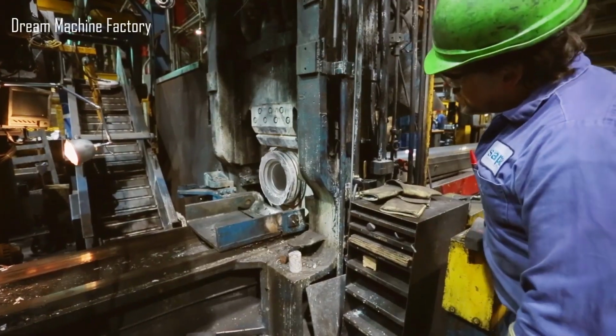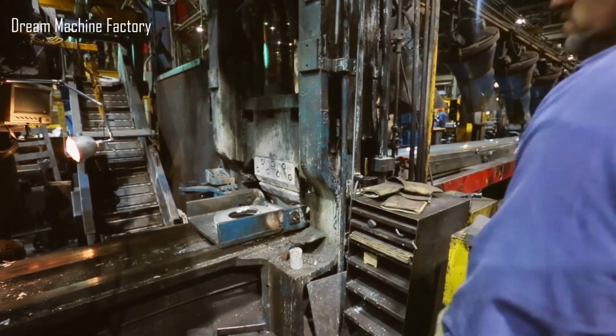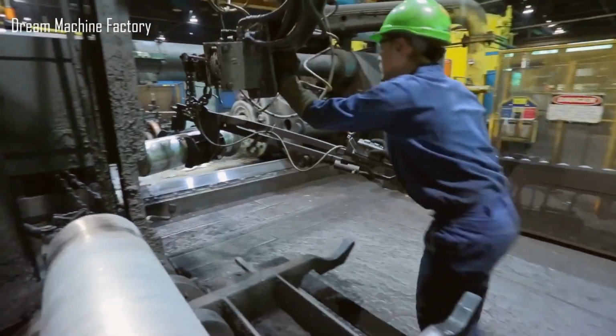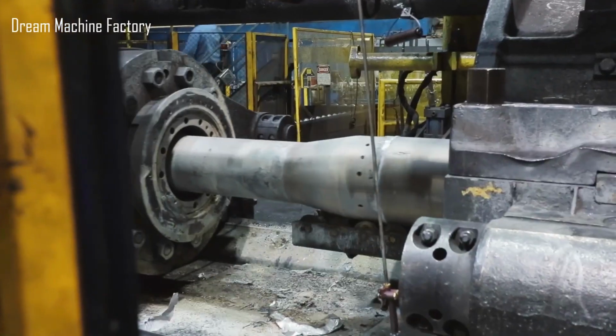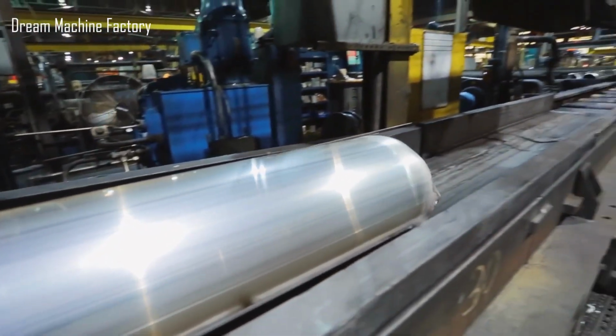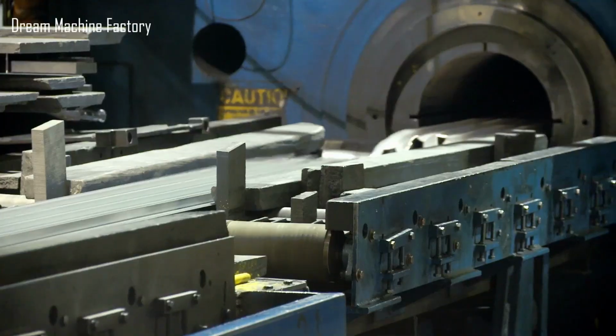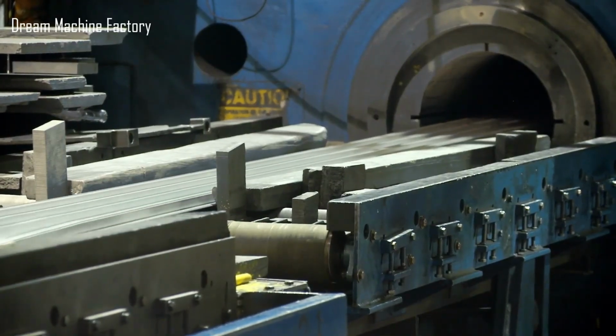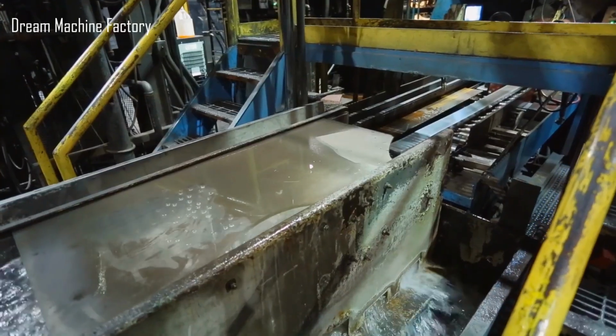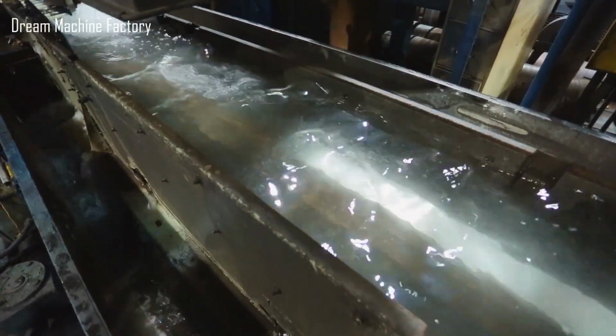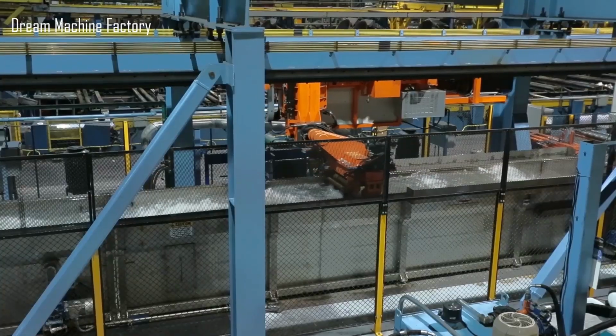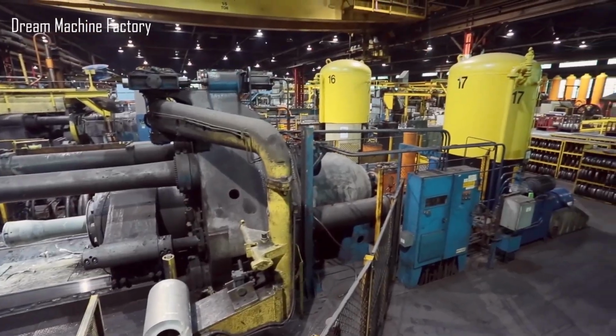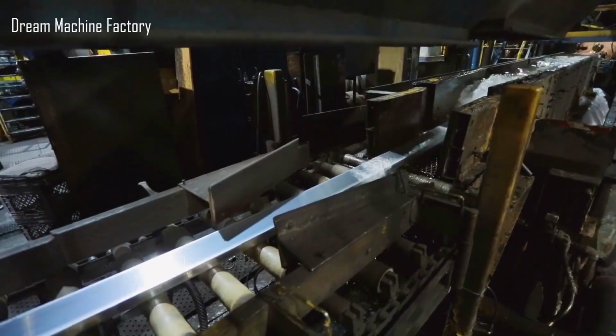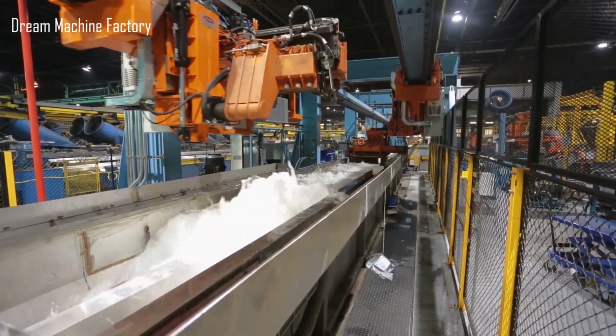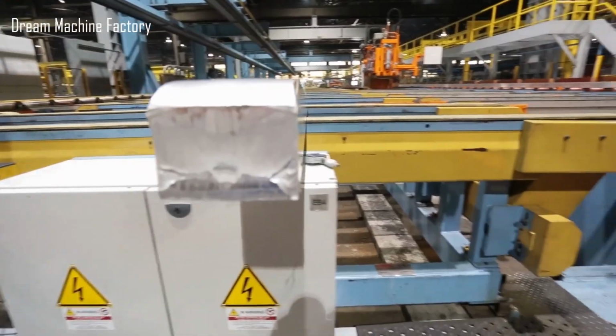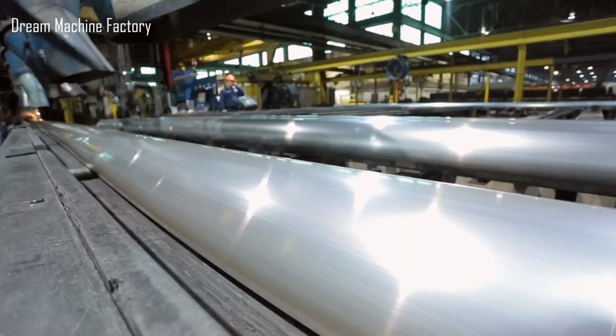Heat treatment is a vital stage in the aluminium extrusion process, particularly after extrusion, to achieve the required mechanical properties. The first and most critical part of this process is quenching, where the hot extruded profile is rapidly cooled using air fans, water sprays, quench tanks, or a combination of methods. Quenching locks in the alloy's microstructure, preserving the phase and element distribution to meet strength requirements. However, rapid cooling can cause internal stresses leading to distortions such as twisting or bowing. To correct this, the extrusions are placed in a stretcher, which straightens the profile and relieves internal stress.